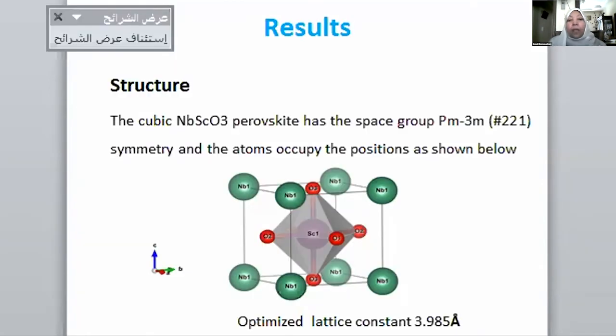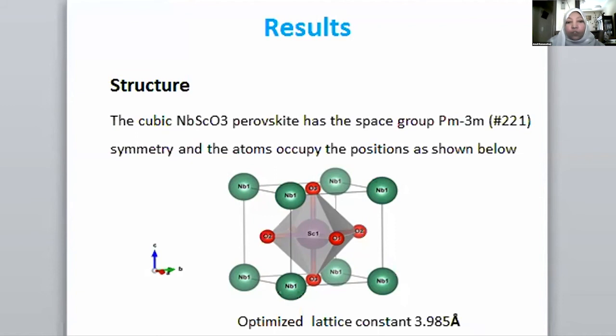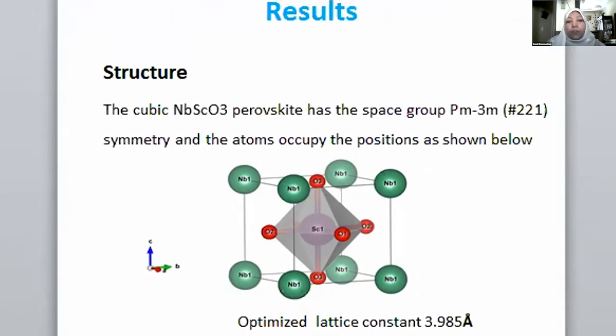Unlike the recent structures that have been used for transition metal perovskites, what I have done is use the cubic structure for the perovskite. In the cubic structure, the corner atoms are the transition metal niobium, unlike in other studies where the transition metal usually occupies the B site, or the body center of the cube. The oxygen atoms are, of course, sitting on the face centers, as you are seeing. Upon optimization, I obtained a lattice constant of 3.985 angstroms, and this was put into the structure file, and all the calculations were done based on this lattice constant value.